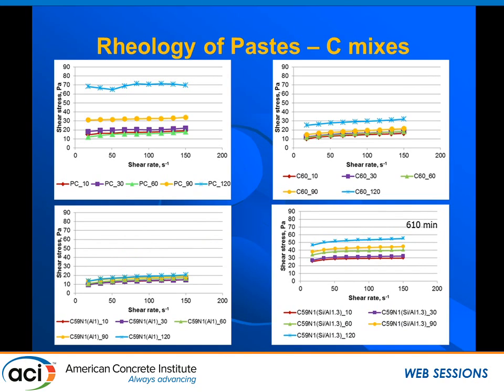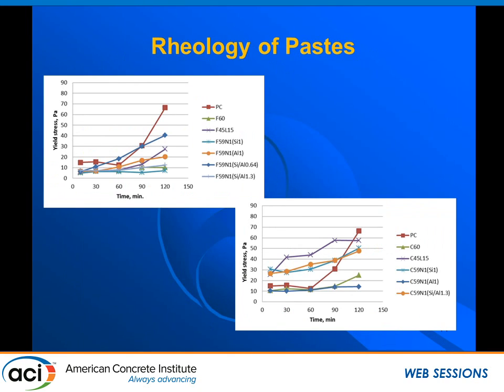Nano Boehmite doesn't seem to help at all. And silica to alumina ratio 1.3 appears to help slightly, but not much.